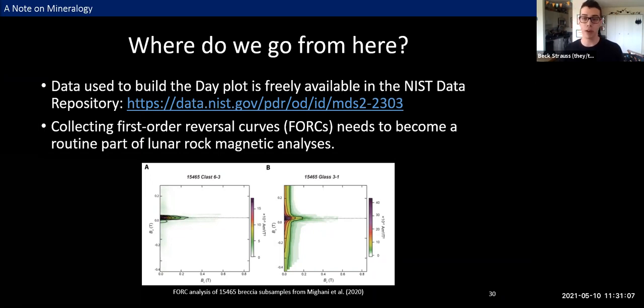I'm showing an example here from a paper that came out last year, just so you have some sense of what this can look like. The clast on the left has this horizontal ridge that extends to fairly high coercivities, and that suggests the presence of single domain and pseudo single domain grains. While the glass on the right, in addition to that ridge, also has this cluster at low coercivity values, which suggests the presence of larger multi-domain grains. And I can tell you all of that totally independent of a Day plot.